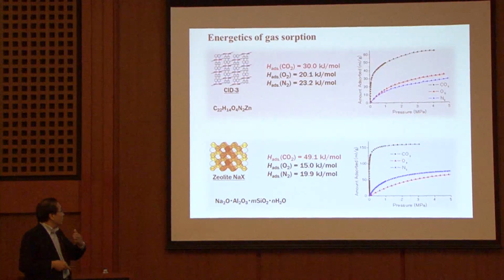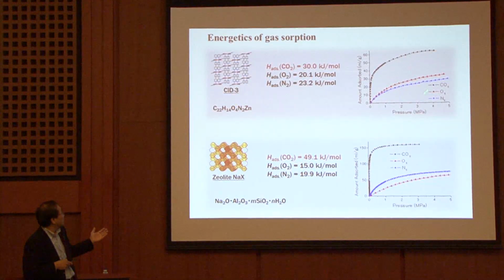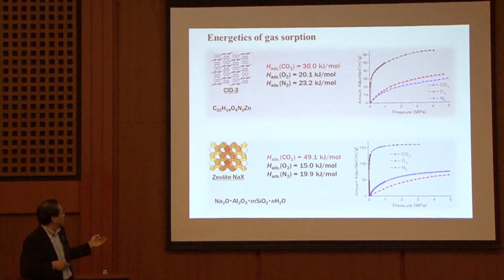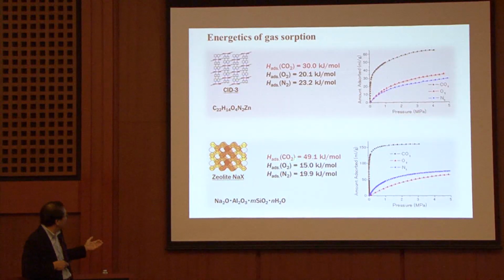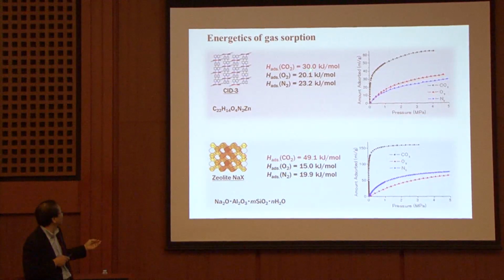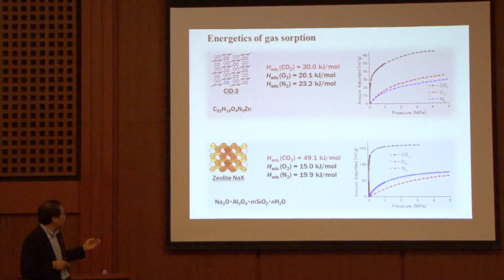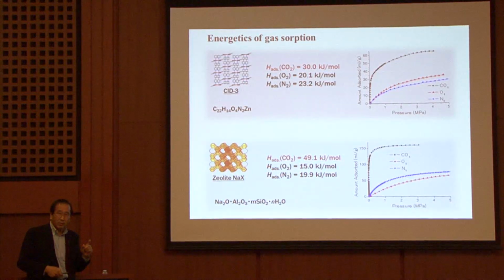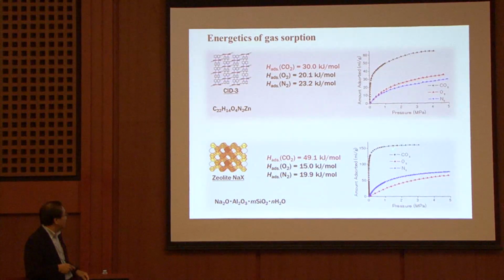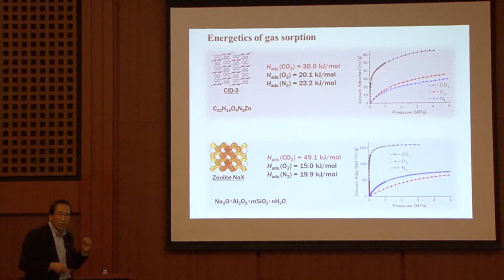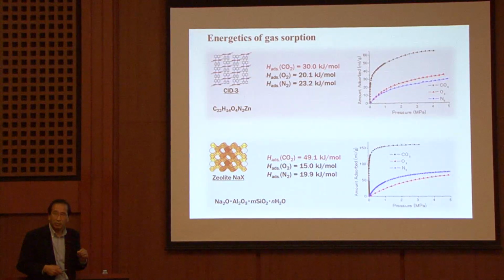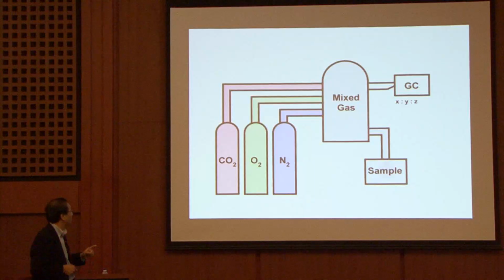So most of the audience judge the results: oh, this is much better than this. Because the interaction energy between the CO2 and the surface is 49 for that one, but in this case it is 30 kilojoule per mole. Oh, this is okay. But the problem is, very high affinity means we need higher energy to remove gas molecules. This is a big problem.